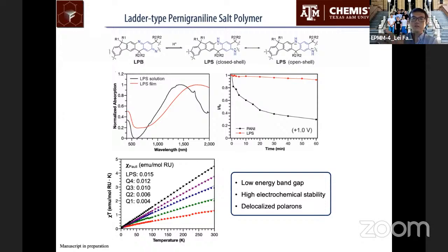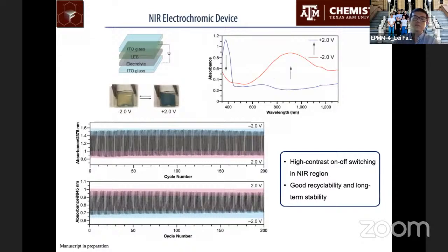So we demonstrate the stability by fabricating an electrochromic device. Here, we all know that polyaniline can change color if you impose redox chemistry on it, but it will quickly decay over time because of the decomposition I showed before. But here, using the ladder type structure, we could maintain a very robust device over hundreds of cycles with a very wide redox potential window. So in this case, this switching process can be maintained in a robust manner because of the ladder type constitution that gives us this chemical stability.